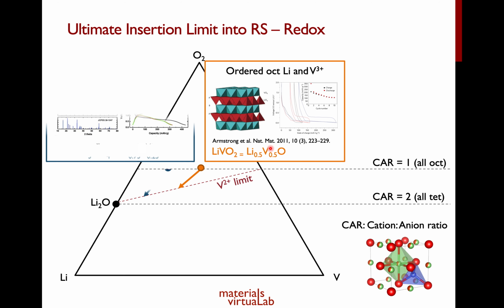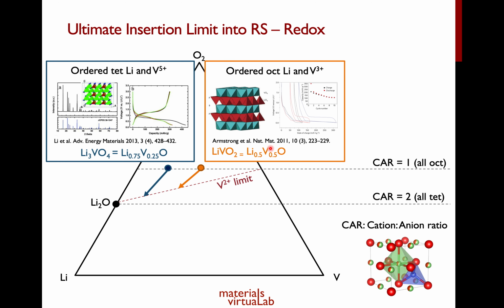Now, there's another lithium vanadate anode that people have investigated, fairly recently in 2013, and that is Li3VO4. If you write this in the rock salt formula, this is Li0.75V0.25O. This is actually not in the rock salt crystal structure. It is still a close-packed oxygen, but now all your lithium and vanadium are in tetrahedral sites, and you start at vanadium 5+. When you lithiate, you follow this pathway over here, up to our vanadium 2+ limit. What you notice about this anode is that the capacity is extremely large, beyond 300 milliamp hours per gram. However, your voltage has increased. Your voltage is now closer to 1 volt, actually slightly above 1 volt.